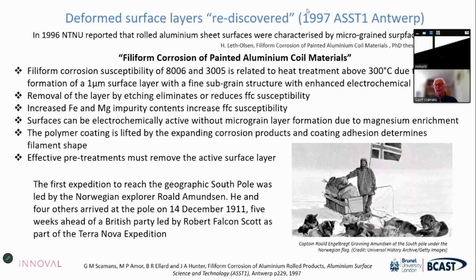And they also said that the control of these surfaces was really important in controlling the surface corrosion properties of aluminium alloys. And they'd found some quite nice things about controlling filiform corrosion by looking at the properties of this layer, and particularly by cleaning it off. But they thought it formed during a high temperature anneal, not during the rolling process. So just like, although the Norwegians were first in getting to the South Pole, as you can see from the illustration behind, they claim to be first in finding deformed surface layers on the surface of aluminium. Of course, this turned out not to be the truth.